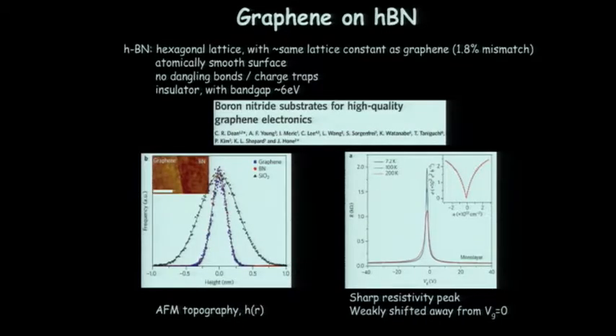And so the original idea then was to try to use something that could be better matched to graphene. And so this is work from Philip Kim and Jim Hone's group using graphene on boron nitride. And so the idea of this experiment was we wanted a better substrate. Ideally, it would have all three of these conditions: be atomically smooth. So the silicon oxide I showed you before has typical roughnesses of something like a half nanometer. Here's an AFM of silicon oxide. So it's not a particularly flat surface for the graphene.